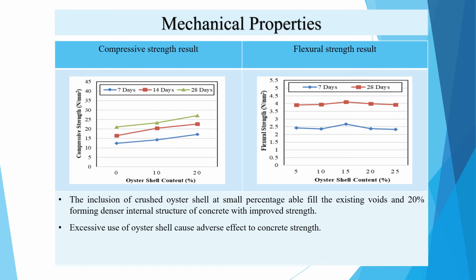The compressive strength and flexural strength of oyster shell replacement are higher than the control mix. The past researchers state that the inclusion of crushed oyster shell at a small percentage is able to fill the existing voids and, at 20%, forms a denser internal structure of concrete with improved strength. And the past researchers also state that excessive use of oyster shell causes an adverse effect on concrete strength.